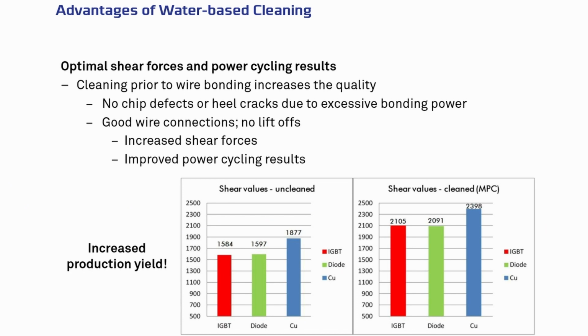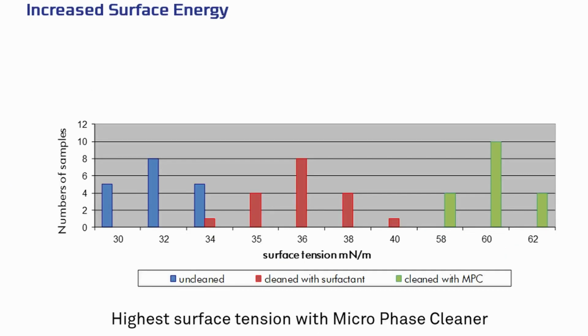Another important thing that also needs to be taken into consideration is the surface energy of the assemblies after cleaning. Because if the surface energy is not good enough, then you would not have good wire pull, and your shear strength is going to be much lower, which will definitely cause a failure when it comes to this type of power electronics.